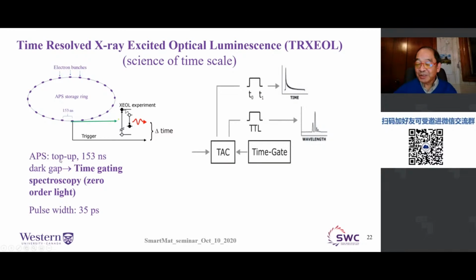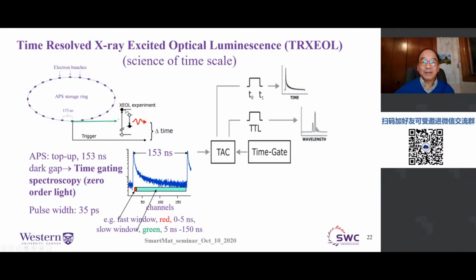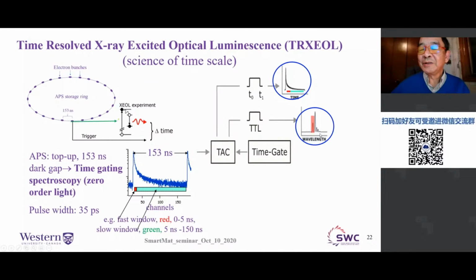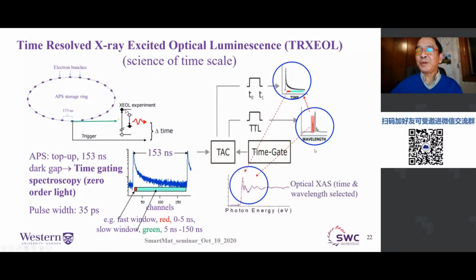Now, synchrotron is a pulse. At the Advanced Photon Source, for example, there's a 153 nanosecond dark gap, right? Okay, so let's say you look at a light-emitting material. When a synchrotron pulse comes in, it starts to emit, and then this is a dark gap. It decays until the second pulse comes in, right? So within this dark window, we can pick a fast window or a slow window, and by doing that, we can see what the emission spectrum is. So, for example, this is the emission or luminescence spectrum within the first 5 nanoseconds, and so on, right? Of course, we can also single out a particular channel and get its decay curve. And we can also use both the energy scan and time gating to do the optical X-ray absorption spectrum. This is the real spectrum based on the time gating and selected wavelength.